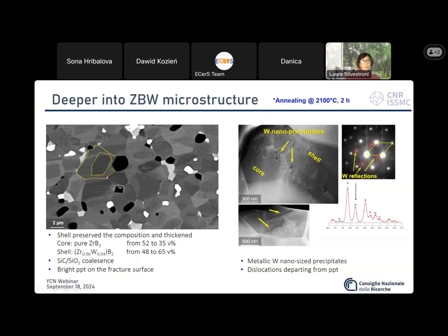I went back to the microscope, this time on an annealed sample of the same composition, just thermally treated to boost the phenomena that were slightly highlighted in the sintered material, and to better evidence what was responsible. On the polished surface, we found that the core-shell was preserved, but just the core was reduced and the shell region was enlarged.